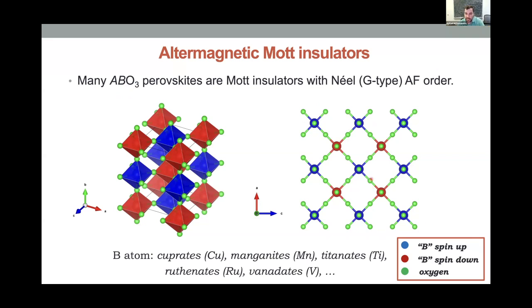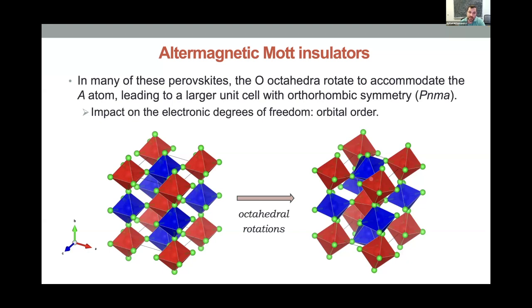But now comes the magic of the lattice, and in this case, chemistry, because to accommodate the cation, the A atom, okay, the vast majority of these perovskites will deviate from this cubic structure. And a subset of them actually go to an orthorhombic structure that goes by the space group Pnma, where the oxygen have these two rotation patterns that now form a bigger unit cell that has more atoms. There's actually 4 instead of just 1.